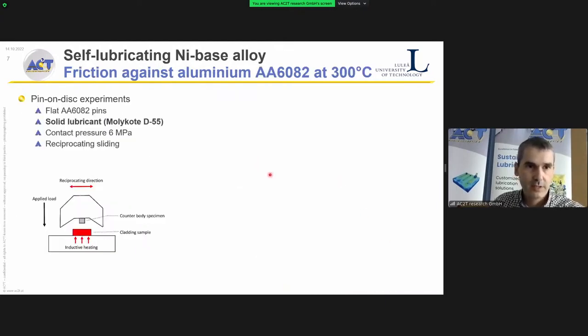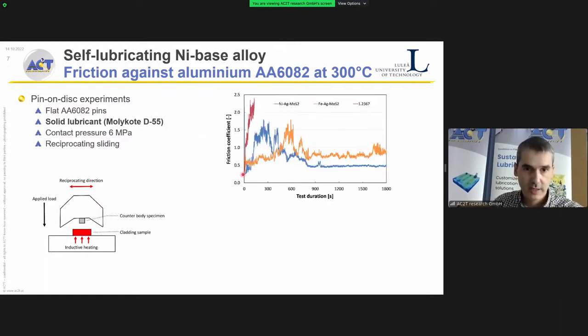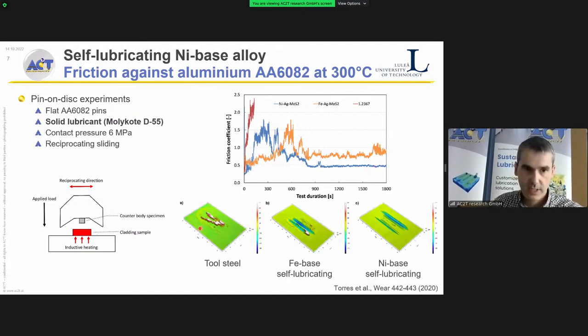Another example, also in this case model experiments, reciprocating sliding against aluminum alloy. In this case, forming of aluminum is very demanding, so we added some solid lubricant and checked what happens when we have lubricant starvation. And you can see, for example, a tool steel starts here with very low friction, but as soon as the solid lubricant fails, friction skyrockets and goes over 2, and we need to stop the experiment due to extremely high friction. And with the nickel base, the blue line, we see that initially friction is low due to the solid lubricant, then you end up building a tribofilm, and at some point friction gets very stable with a value of 0.5 and could continue during a much longer period. And also in this case, we see that we switch from adhesive wear to mild abrasion.